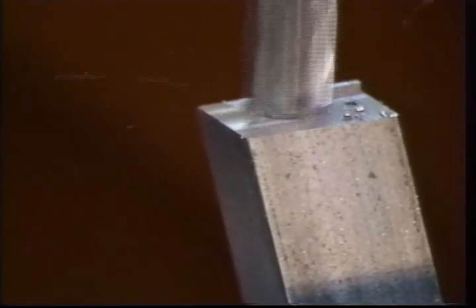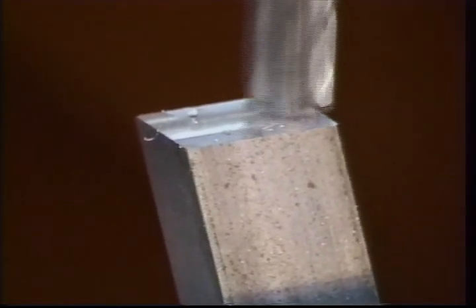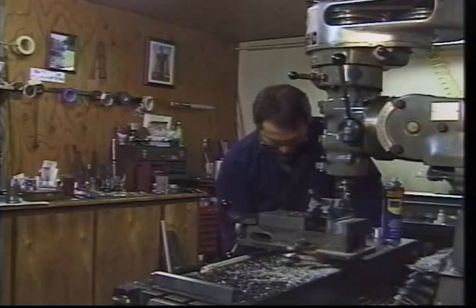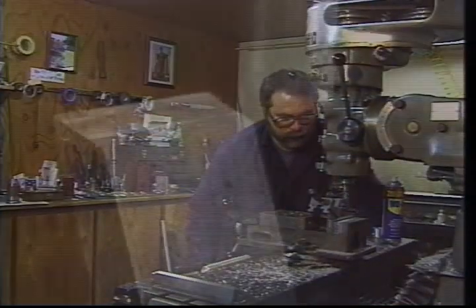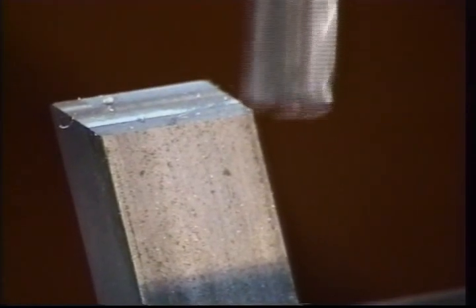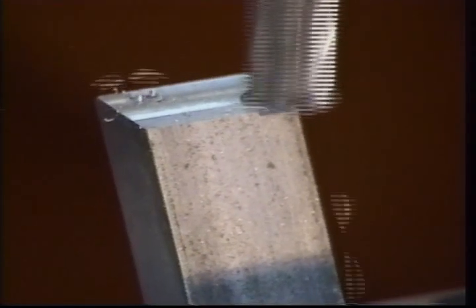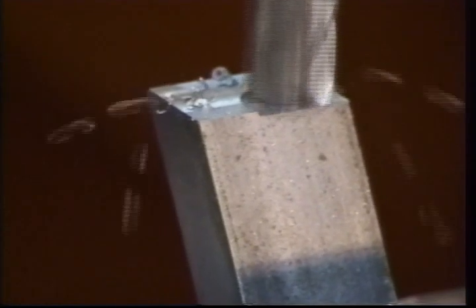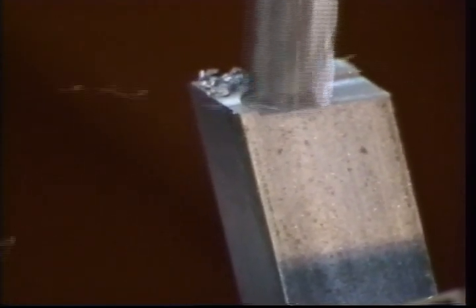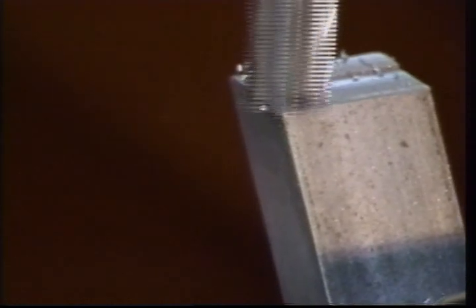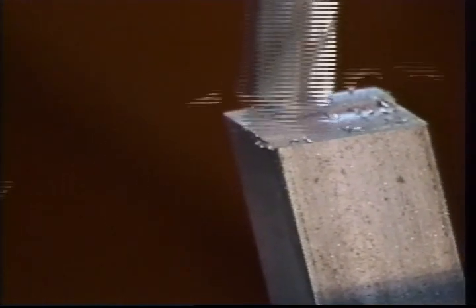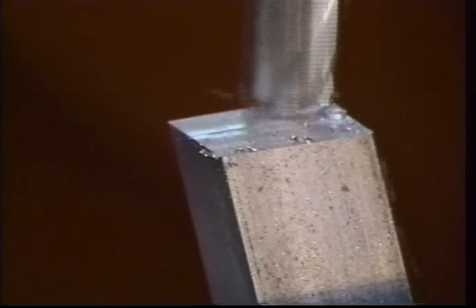Index our cutter over. Come across it for the second pass. About another 20 thousandths ought to do it. You can also watch the chip color. You can see the chips are coming off in a nice shiny color. They're not turning straw or blue color, again, indicating too high of an RPM or too fast of a feed rate. We're not using any cutting fluid on this particular job. We're machining a leaded type material that machines really well.